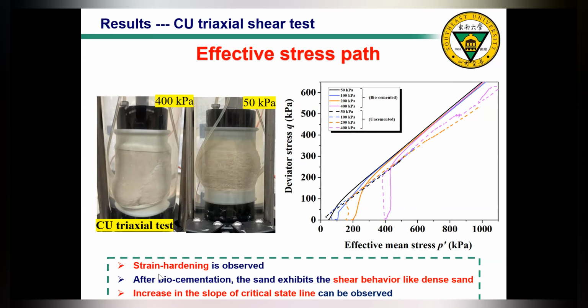And secondly, after biocementation, the sand exhibits shear behavior like dense sand. So compared with the uncemented case, the effective stress path shifts to the right. And this is especially true at lower effective mean stress. So for clean sand, it's more like loose sand. However, after biocementation, it becomes more like dense sand.